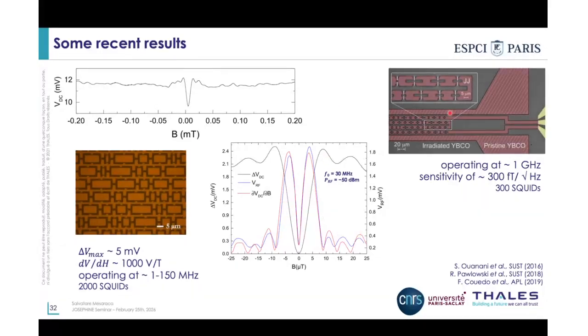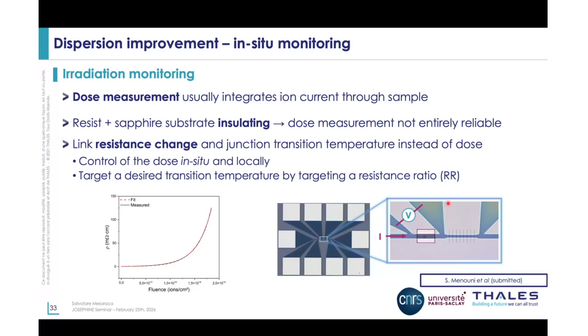So this is about some results that we got on samples. Regarding sensitivity and homogeneity of the samples, we realized that we are a bit far away from what could be the absolute goal for this kind of devices. Especially about homogeneity, we realized that there are huge differences between different ones, because again, it's very tricky to control the ion radiation, which has a huge impact on the TC, on the change of the TC in the irradiated area, and also the E-beam part where actually we make the slits. So a huge part of our work is actually on improving the dispersion on this kind of devices.